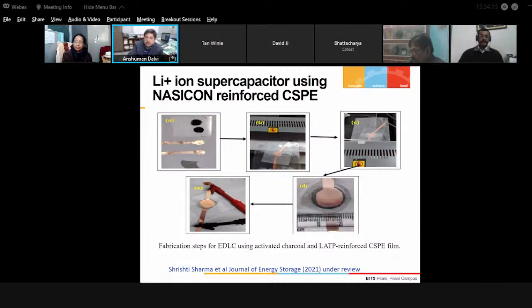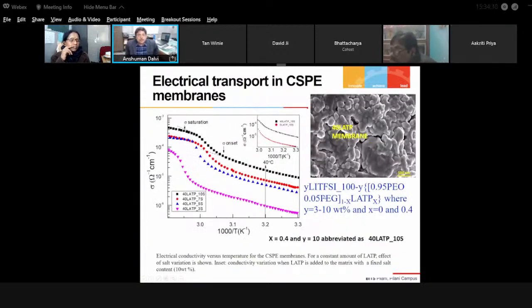We just let it go through the lamination machine, and then it gets laminated. About 70 degrees of temperature, which is a little higher than the melting of the polymer, is achieved, and this establishes good contact at the interface. These steps are simple, and one can prepare these supercapacitors. These are now all solid contacts at the interface.